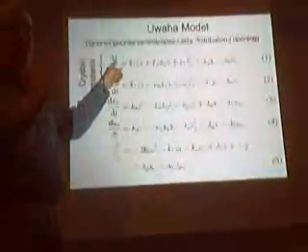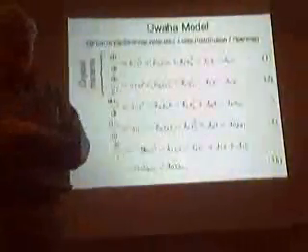Okay, so this is Uwaha's model, and we'll just go through it. That's a picture of his paper, the page, and we'll just go through and show what's in it. Okay, first, this is the differential equation, the change in time of the crystalline material, the big crystals that grow because the solution is supersaturated with respect to these big crystals. And notice incidentally that this ignores particle discreteness. The only thing it talks about is how many molecules are in that population, not how many are in a given particle. The only thing that you know about the particle is it's supercritical, so that it will grow and not dissolve. Or anyhow, you can neglect the possibility of its dissolving, that is going away, becoming smaller.